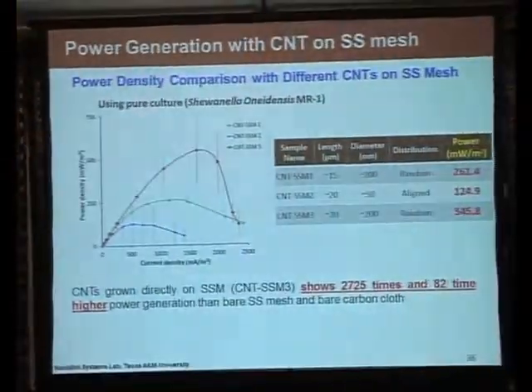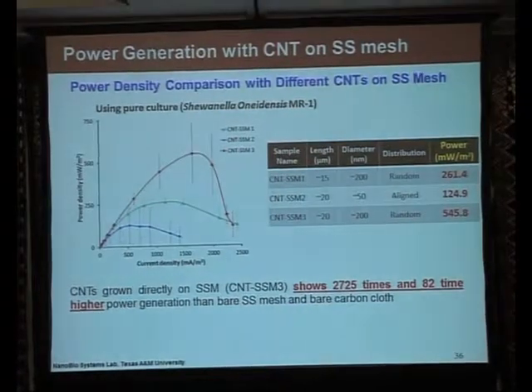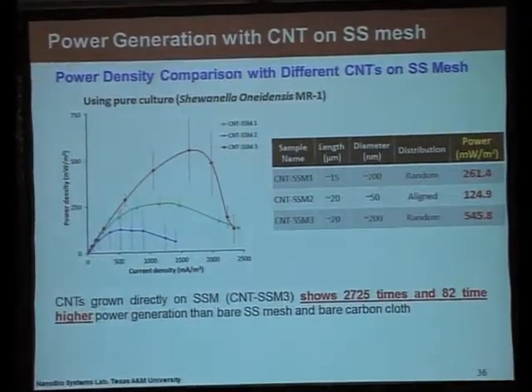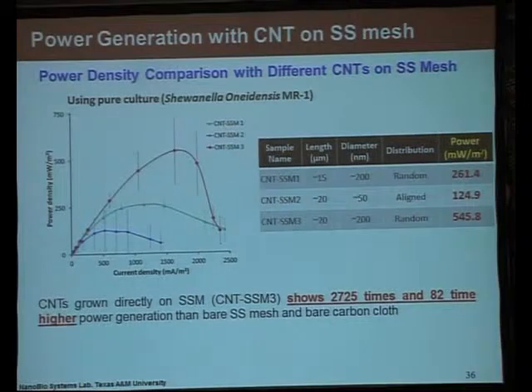Now we're comparing the power density of the CNT-synthesized porous structure to the 2D structure without the carbon nanotubes. As you can see, the CNT directly grown on the stainless steel mesh shows almost more than 3,000 times higher electricity generation compared to a bare electrode. And note that this is using a pure culture.